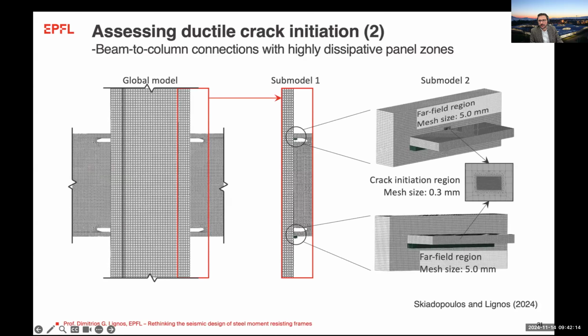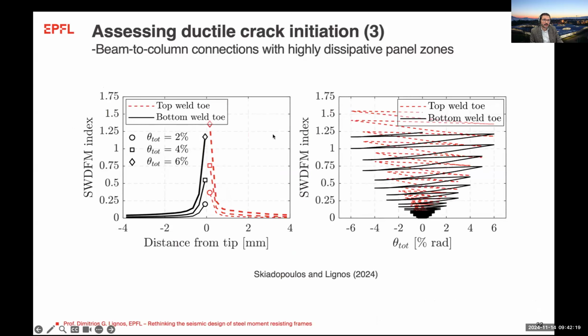And based on our work, what we've seen is that, in fact, if you use some of these micromechanics-based models, ductile crack initiation would not commence prior to an MCE level event. In fact, it would happen at a much larger drift in the range of 5 to 6% that I mentioned before, where the structural behavior is going to be controlled by P delta and not by crack initiation in this case.